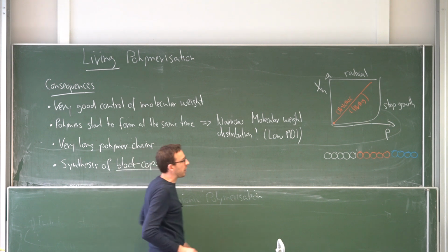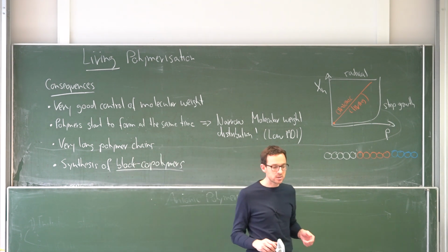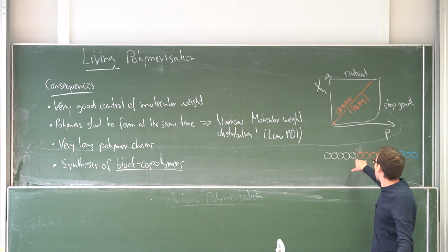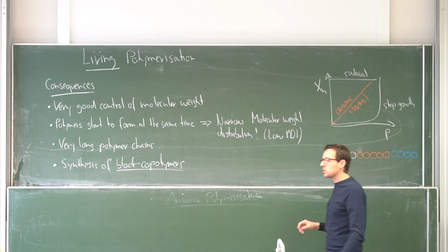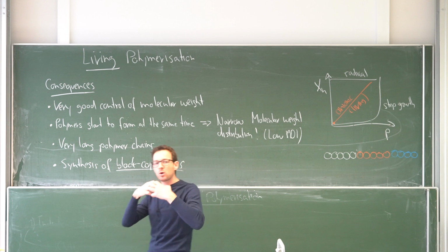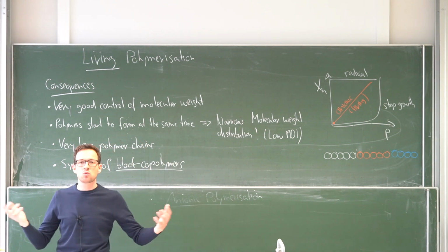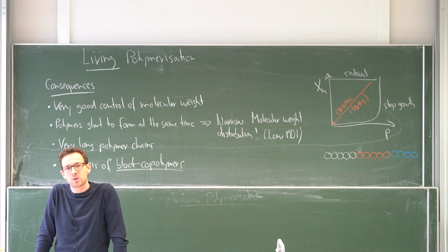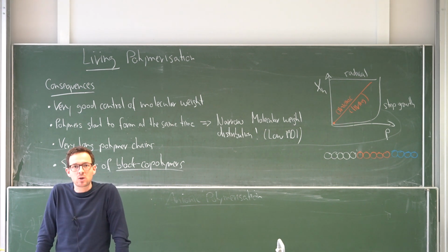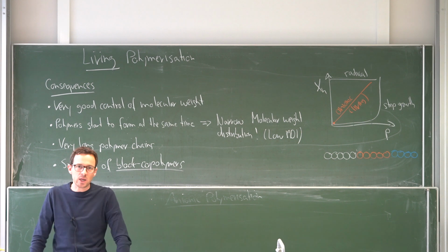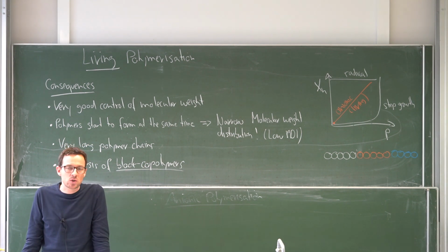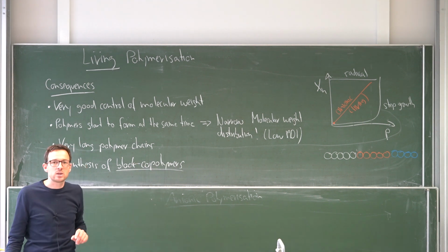And that is not the only thing. What we will discuss in the next lectures is that polymers do not mix very well. And if you have a block copolymer, it allows you to chemically force or bond together polymers that actually do not want to mix. And this generates very fascinating properties because if you want, you force the molecules in a situation where they do not want to be, and they try to phase separate and come up with very elaborate structures to avoid their phase mixing.